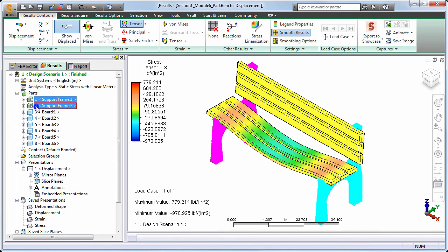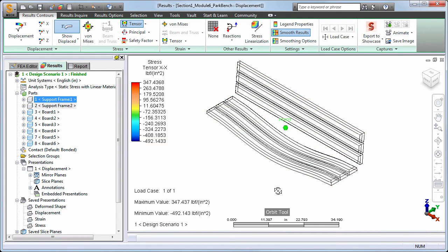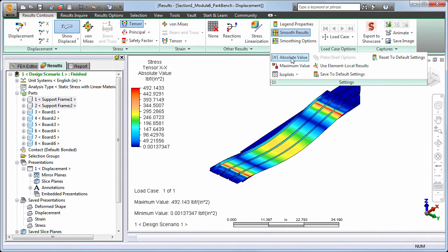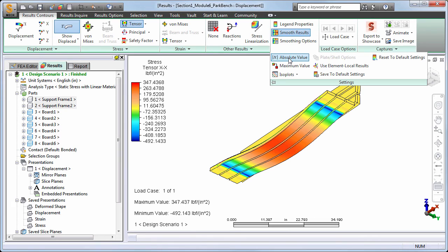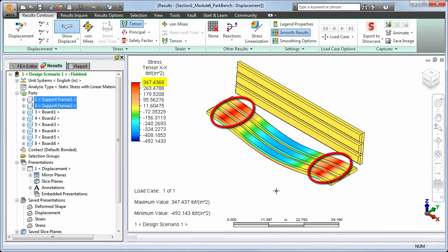We should hide the cast iron parts so that the legend and color contours reflect the range of stresses in the boards only. The greatest magnitude of stress is negative, or compressive, and occurs where the boards contact the support frames. If you prefer to render the stresses with the greatest magnitude in red regardless of the sign, activate the absolute value option in the expanded portion of the settings panel. However, it is a good idea to consider the sign of stresses in wooden parts, since the tensile and compressive strengths typically differ in any axis direction. The maximum tensile stress occurs at mid-span along the bottom surfaces and slightly inbound of the support frames on the top surfaces. The reason for the high tensile stress on top is the rigid, bonded connection of the boards to the support frames — the boards behave like built-in beams rather than simply supported ones, resulting in a high moment near the supports.